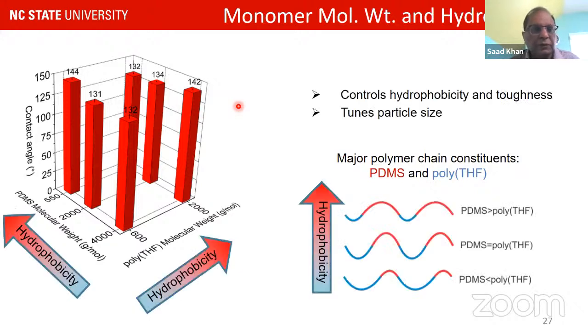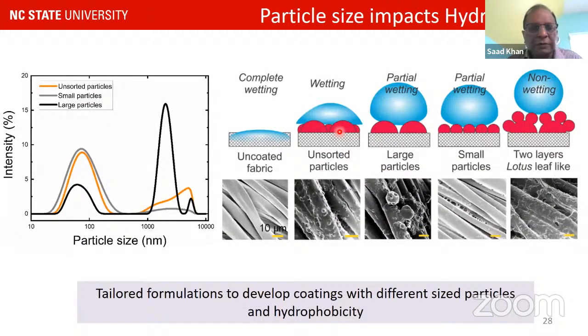If we look at it, going to lower molecular weight here, we get more hydrophobicity, and going to higher molecular weight here, more hydrophobicity. So we can tinker with the hydrophobicity by changing the molecular weight, the ratios, and so forth. The main two components are PDMS and poly-THF, and we can tune the particle sizes as well by playing around with this. When we get these dispersions, they have multiple size scales, but they usually fall under two, plus some unsorted ones.